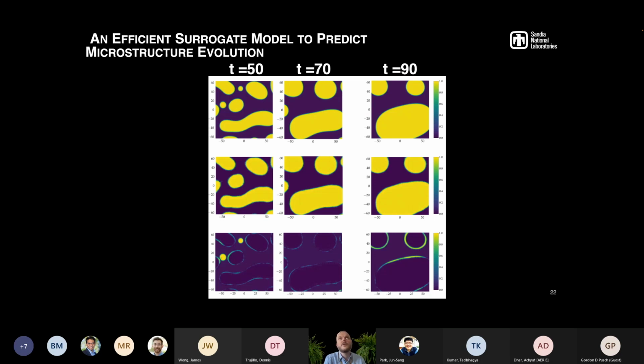Here, what I'm showing you on the screen is, the top row shows the evolution of the microstructure as predicted by the high fidelity phase field simulation. The middle row shows the predictions given by our DeepONet architecture. And the bottom row shows the difference between the two. And so what you see is that overall, we have a very good agreement between predictions given by our DeepONet architecture as compared to the direct numerical simulation.